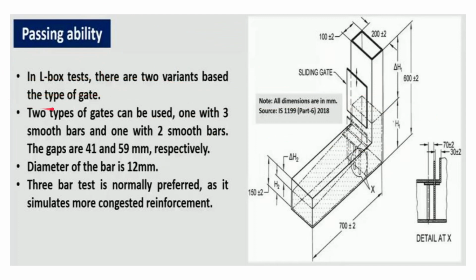There are two variants based on the type of gate. One gate uses 3 smooth bars and the other uses 2 smooth bars. The gaps are 41 and 59 mm respectively, and the diameter of the bar is 12 mm. The 3 bar test is normally preferred as it simulates more congested reinforcement, because our aim is to find out the passing of the SCC through congested reinforcement without segregation. The more the congestion, the better the testing. All these are given in IS 1199 Part 6: 2018, as I mentioned, so for further details you can refer to the code.